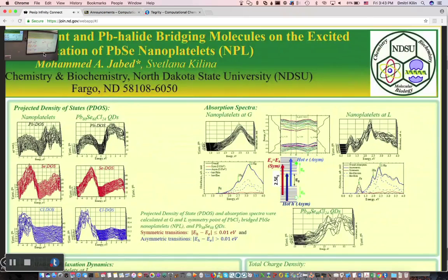And the gamma point is because if we look at the bands, these bands are very continuous compared to the L points. So that continuity gives us a higher coupling between the bands, so it's relaxing faster. But at the L point, they have a subgap. This subgap makes this zero order relaxation into a kind of second order relaxation. Then it's relaxing to the subgap, and then it takes time to relax to the frontier. Oh, you still have a subgap at the gamma point, right? For electrons especially. Maybe not so much for holes, but for electrons they are kind of split levels.